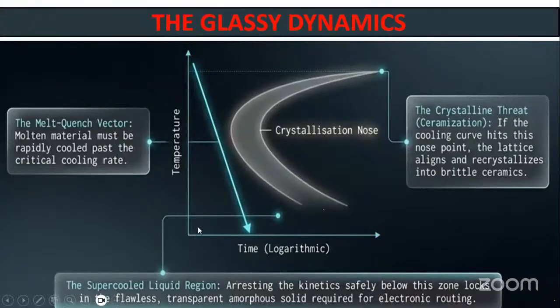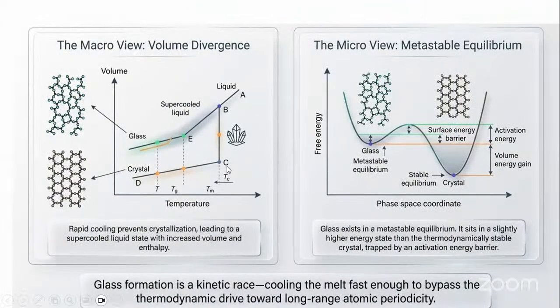If you observe this time-temperature transformation curve, you can see that there is a C curve, and a line being drawn. Below the nose point of that C curve, the material is undergoing supercooling. But at that particular nose point, the material undergoes crystallization. To further visualize this, a perfect crystal has a unique melting point. The moment you heat it, it is solid, and at some point it becomes completely liquid. But with glass, it undergoes an expansion, and it knocks on a door called the glass transition region. After surpassing that region, it undergoes the liquidus phase.